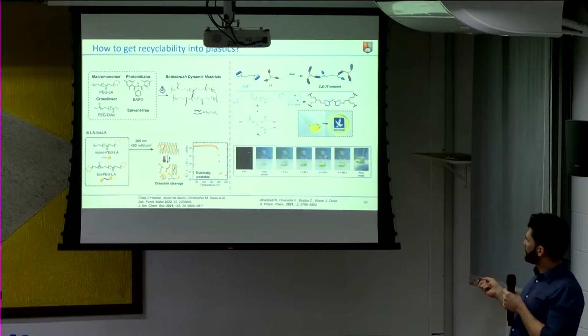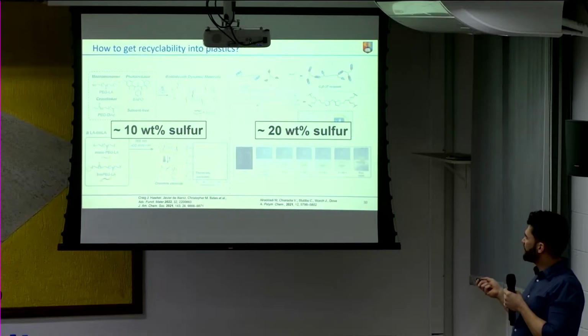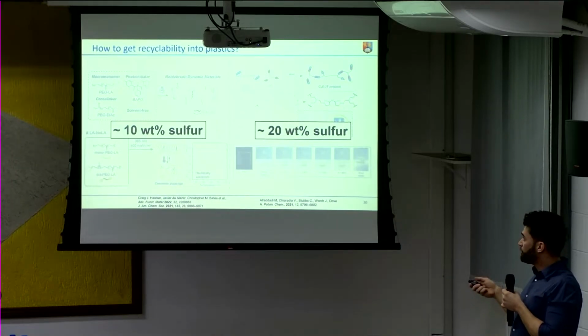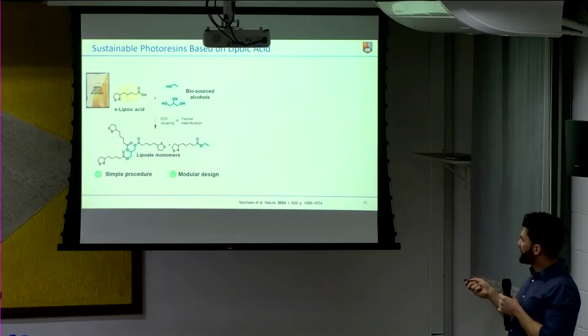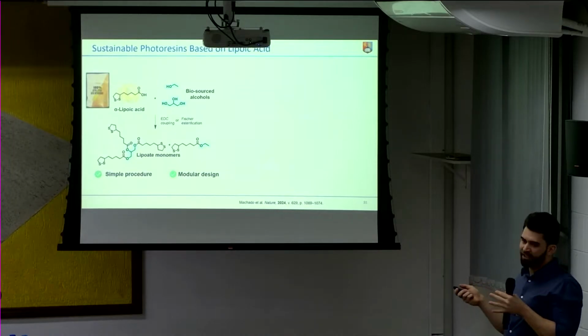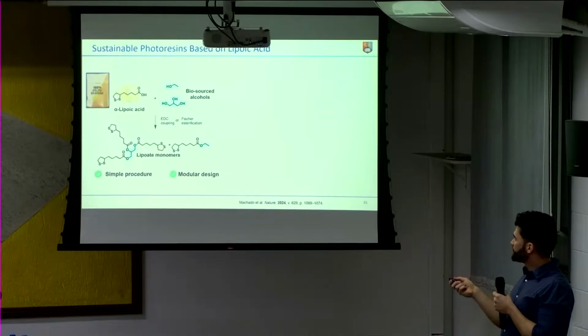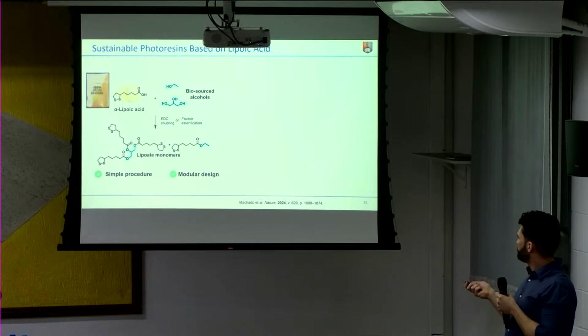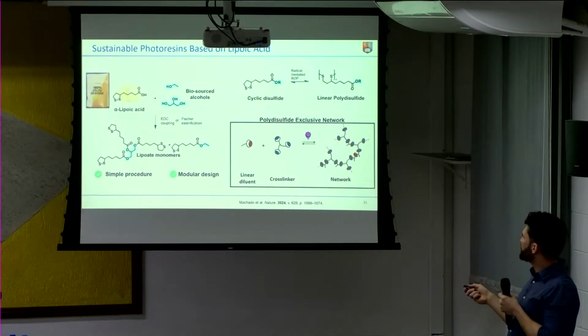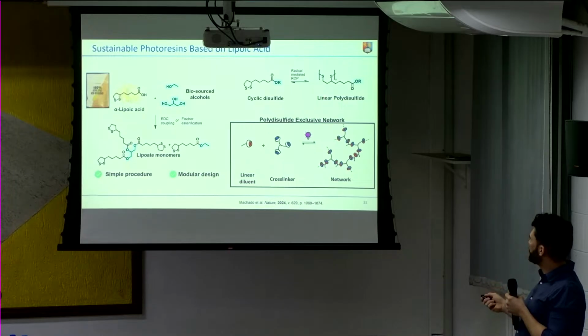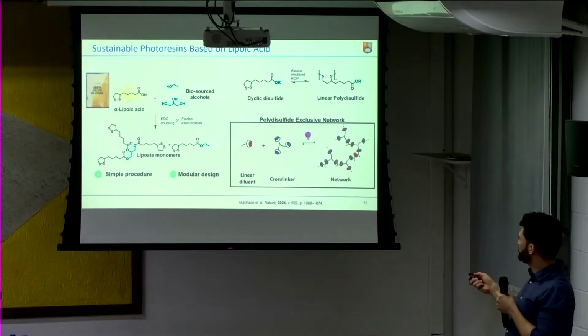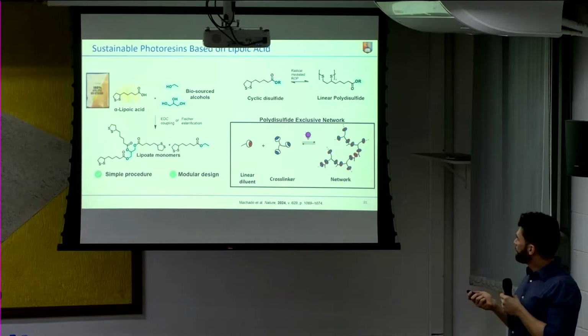And we knew for a fact that we could fully depolymerize those materials, and we thought, why? So we did a calculation, and that's because we had more sulfur in our system than they had. But inspired by these works, we decided to design a fully polydisulfide network based on lipoic acid. So we just made some monomers with biosourced alcohols. Simple procedure, just changing the alcohol in the esterification here. And then we can create a fully polydisulfide network through radical ROP of the dithiolane ring.